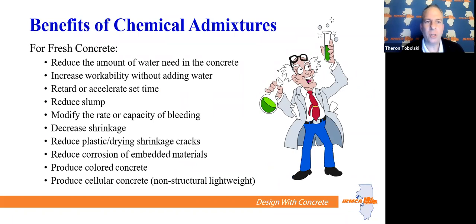Benefits of chemical admixtures, right? You can reduce the amount of water needed in concrete. You can increase workability without adding water. You can retard or accelerate the set time. You can reduce slump. You can modify the rate or capacity of bleeding. You can decrease shrinkage. You can reduce plastic or drying shrinkage. You could reduce corrosion. You could produce colored concrete, or you can produce cellular concrete. So there are a lot of benefits to using admixtures in your concrete.